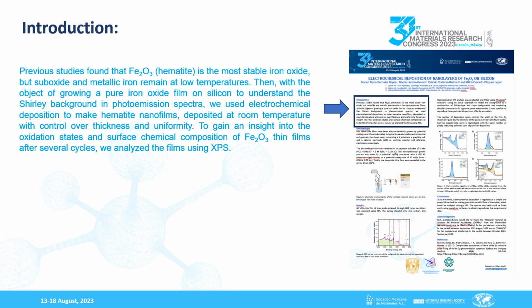To overcome this problem, we propose to make hematite nanofilms using electrochemical deposition, providing a convenient way to synthesize films and control the thickness in relation to the deposition cycle. In addition, it is a low-cost option that grants uniform large area deposits, and it can be performed at room temperature.